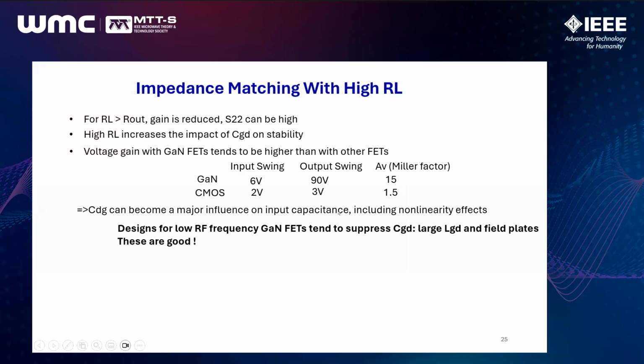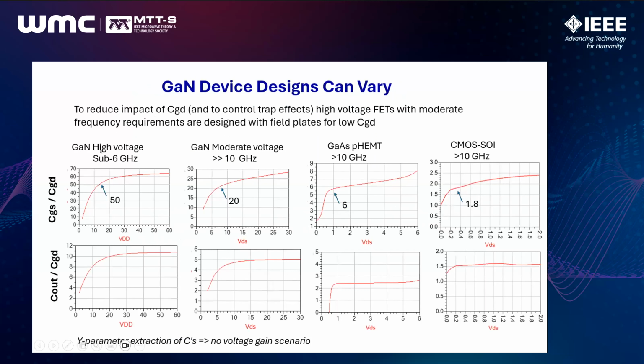So CGD can have a major influence on the capacitance of the device, including nonlinearity effects and the injection from the output to the input side. So these are things that are recognized by gallium nitride FET designers. And so for low frequency applications, it is useful to suppress CGD by using a large gate-drain distance (Lgd) and field plates. These are good. So for example, if you look at devices of gallium nitride used for high voltage, 100 volts or above, in sub-6 gigahertz applications, you find that the ratio between CGS and CGD is quite high, of order 50 or so. A gallium nitride device that is applied at higher frequencies tends to be designed with a lower ratio of CGS to CGD, and this might be in the range of 20 or so.